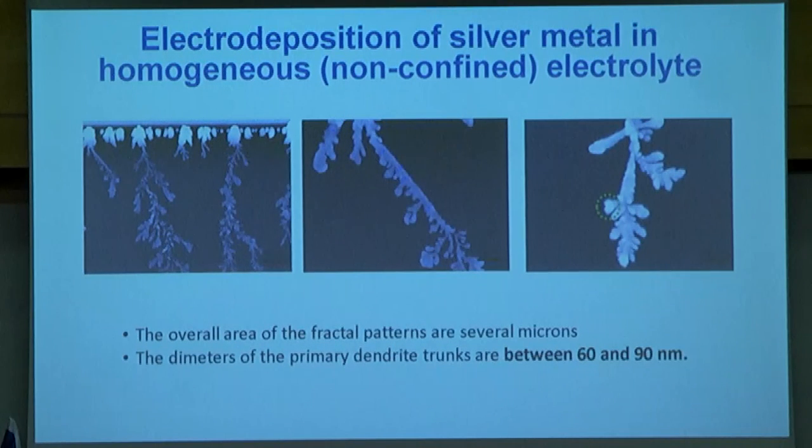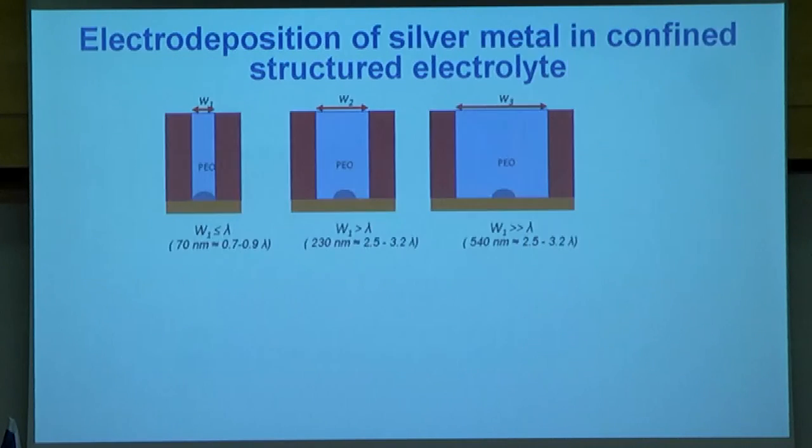What is nice with this coplanar electrode is that you can take it immediately to the SEM or the TEM if you want. And you can make pictures that show you really the dendrite without any destruction, and take those sizes and really define lambda critical. There is a way to do it on the sizes here, but on the right you can see really the particle splitting, the heart shape, it's really where it starts. We didn't catch it, it was by accident, but you can see the nice splitter.